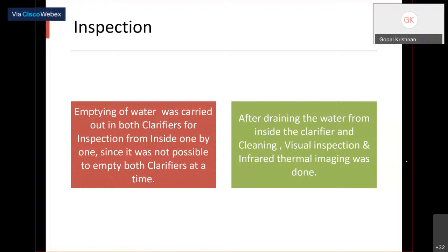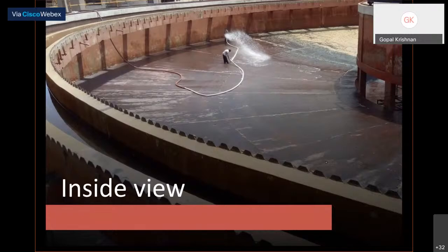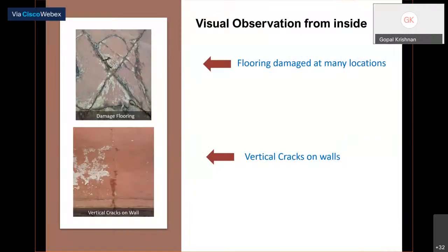We emptied the clarifier and inspected it clearly after draining the water and cleaning. Visual inspection was carried out along with infrared thermal imaging to identify the spots. This is the cleaning, the very first step after emptying the tanks. Then you can see the floor damage, cracks everywhere, and vertical cracks everywhere through which water is seeping from inside. We have taken the picture.